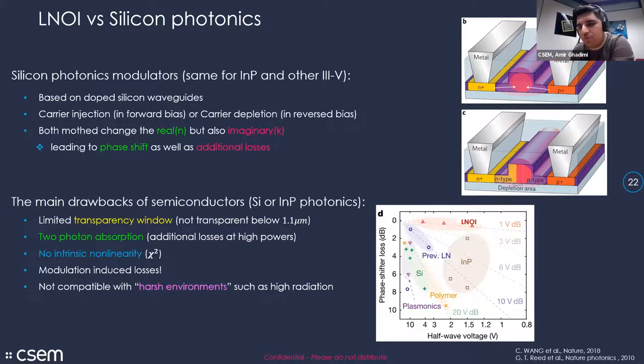Plasmonics, we all know, is the worst because of the metal in the dielectric, with polymers in the same ballpark. With indium phosphide you can do a little bit better, but look at LNOI. Since the effect is intrinsic, a Pockels effect, you can do very deep modulations with little to no additional losses. So we are below 1 volt dB. This is really the advantage of lithium niobate. We can do it really fast, but also at very low losses, power consumption, and very low V-pi. Making modulators below 1 volt is very common these days in our group.